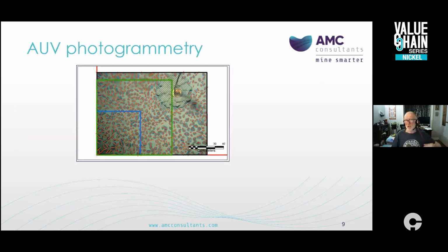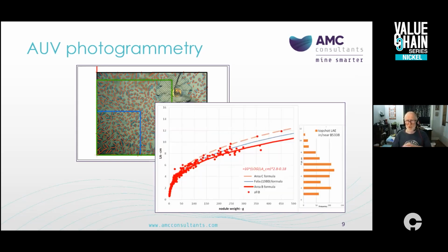As I mentioned, AUVs can also be used to obtain close-up photographs and video of the seafloor. Photographs have been used by commercial explorers since the 1970s to estimate polymetallic nodule abundance. A predictive relationship can be established through measurement of each nodule's long axis and its weight. This graph shows nodule weight plotted against nodule long axis length. By measuring the long axis digitally and using the calibrated relationship, the total weight of nodules within a calibrated area of seafloor can be estimated. This process is known as long axis estimation.